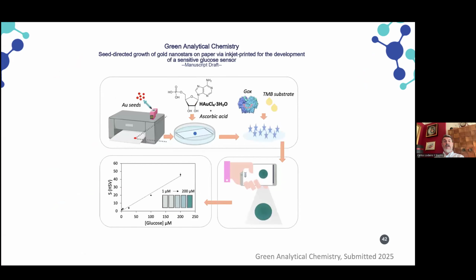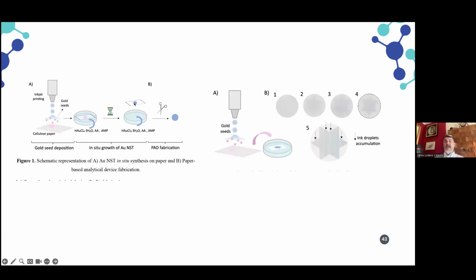And we created something in collaboration with the part of our group that is working in biochemistry, in proteomics, to create sensors. In this case, we use these nanoparticles to obtain a sensor for glucose that is useful and readable with a mobile phone. So in this case, we use the gold nanoparticles, in which we introduce the ascorbic acid and the molecule. We create the nanoparticles in a paper, and this paper can be printed, for example, via an inkjet printer. So we can use our solution as an ink, and then the ink solution is deposited in the paper, and then we can create a shape around the nanoparticle.